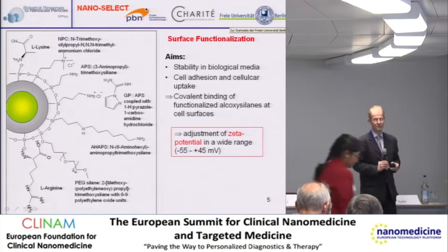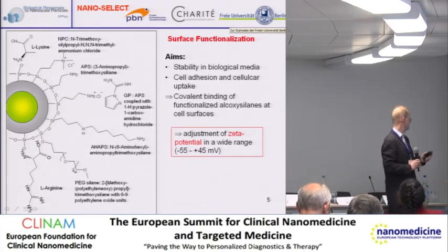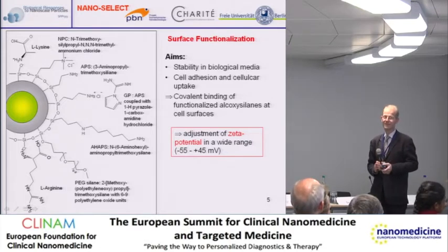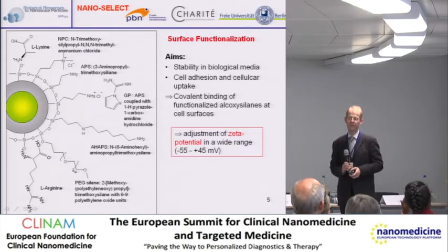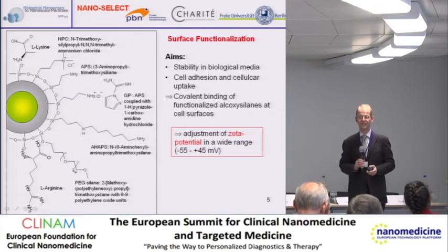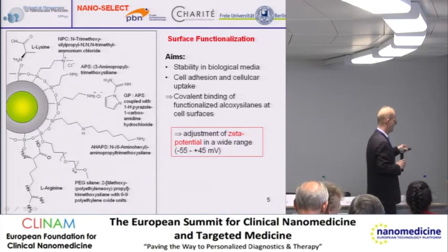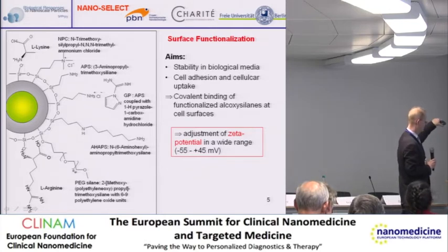We'll not go through all of them, but you see here that the surface charge that leads to electrostatic stabilization of the particle, so that there is no aggregation in a solution or cell media, can be well adjusted by the zeta potential.